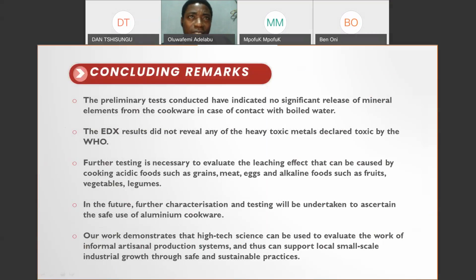Then the EDX result did not reveal any of the heavy toxic metals which had been declared toxic by the WHO. However, we admit that further testing is necessary to evaluate the leaching effect that might be caused by cooking acidic foods such as grains and also alkaline foods such as fruits or vegetables. So in the near future, further characterization and testing will be undertaken to ascertain the safe use of aluminum cookware, especially those produced in Shaki Town.